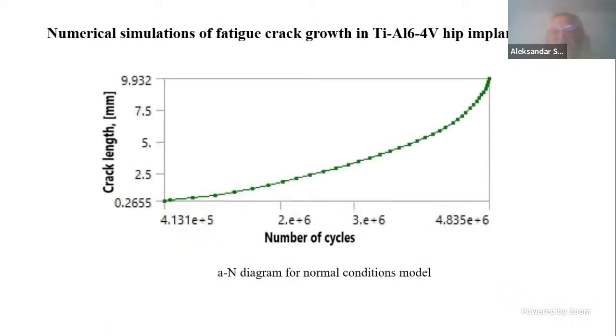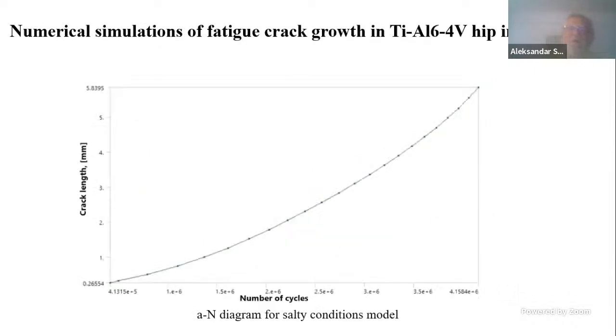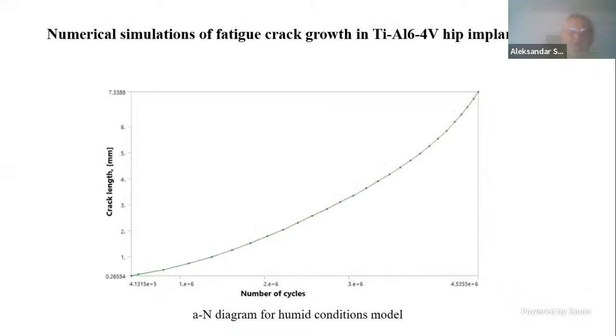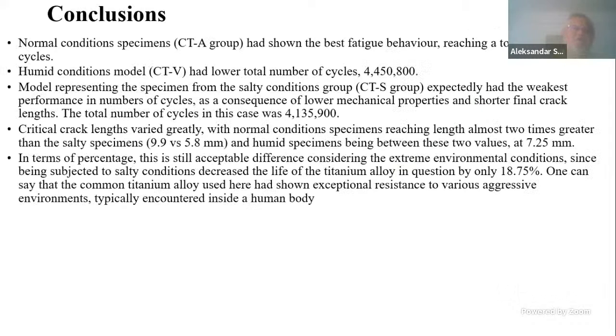And here are the results, just 3 different curves for crack length versus number of cycles. We go quickly through that. The second one is for the salty conditions, and the third one is for the humid conditions. So once we saw these results, we can conclude that 4,835,000 is the best fatigue behavior for normal conditions, of course.